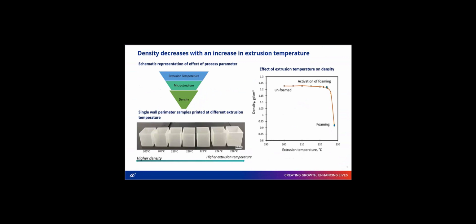As I said earlier, the extrusion temperature affects the microstructure and through which the density is varied. So we studied the effect of extrusion temperature on the density by printing single wall perimeter test cubes with different process parameters starting from 200 degrees Celsius to 228. And we analyzed the density of the sample and we could see the foaming alter the density. At 228, we could see maximum foaming and a decrease in the density and also an increase in the wall thickness with the increase in the temperature.